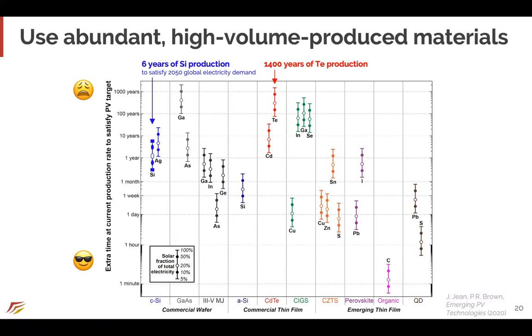One more thing is that because these emerging technologies use abundant materials that are produced in high volumes, they can often reach terawatt scale deployment without requiring a lot of growth in production of the raw elements. Compare silicon, which needs about 6 years of silicon production to satisfy all world electricity demand, if you were to use 100% silicon PV. For tellurium, you need something like 1,400 years, and this has been kind of the dead horse that's been beaten a lot for CdTe. I do want to emphasize that you don't need to satisfy all electricity demand to be a useful technology, so I don't want to downplay this.